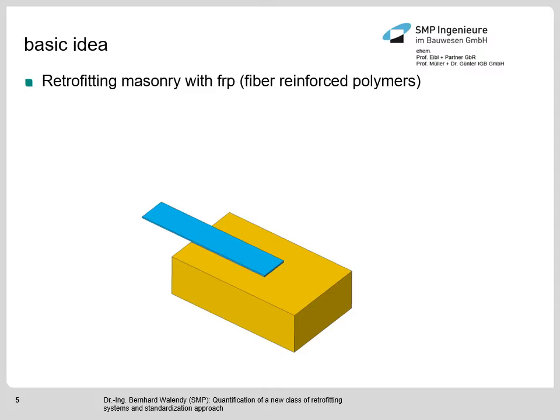And especially for non-load bearing walls, this masonry endures out of plane loading or bending load, and the fiber reinforced polymer stripes during the load situation have to endure tensile force, which is shown here. And during this load situation, there is bond stress transferred between the fiber reinforced polymer and the masonry itself. And the standard failure mode is brittle cohesive failure within the masonry stone. This is the standard failure mode for epoxy-based systems.